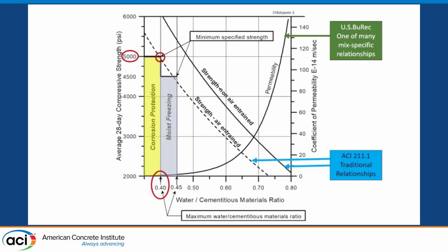without the de-icing salt, we want to be right around in here at a water-cement ratio of 0.45 or less. That would intersect the 211.1 data at about 4,500. So a number like 4,500 becomes a minimum specifiable for a freeze-thaw environment. If we then say, well, I need even lower permeability, let me go down here to around a 0.4 to come down on this permeability curve. Yeah, that's going to help keep the water and the salt and the oxygen and the CO2 and the pets and the small children from being sucked into the concrete. And then we run that up, and that's going to intersect the air entrained curve at about 5,000. All right, so there's some justification for these numbers.